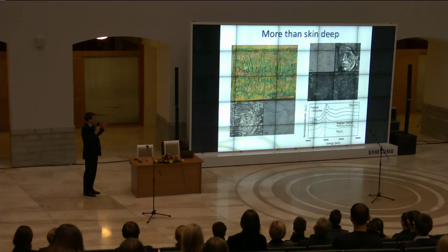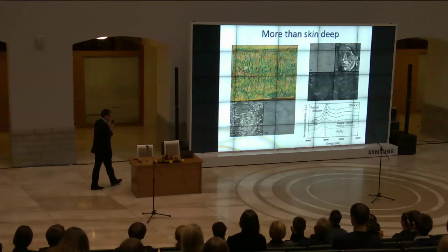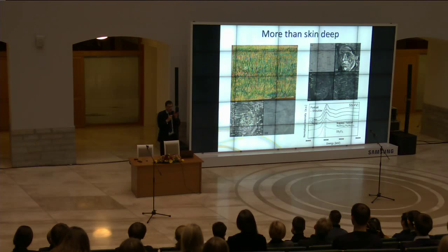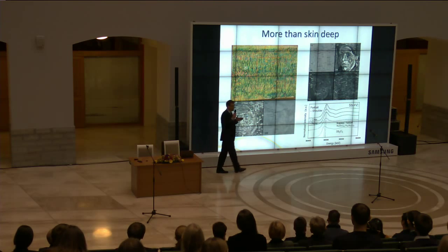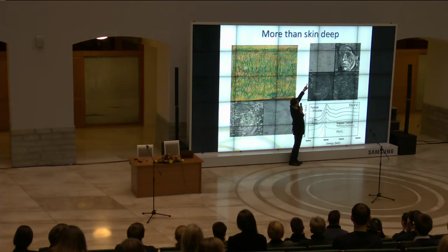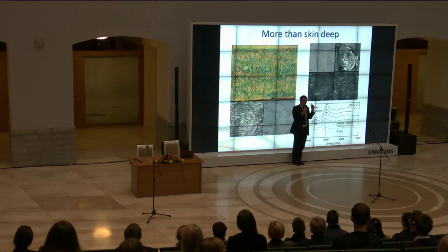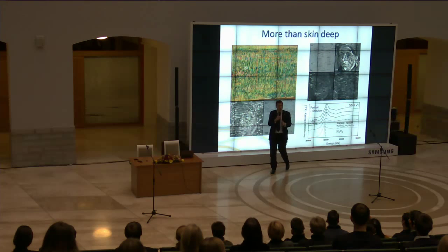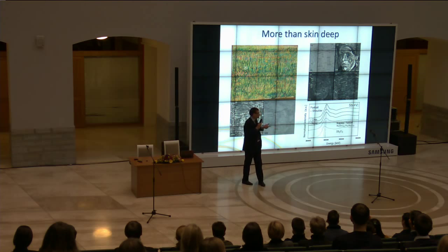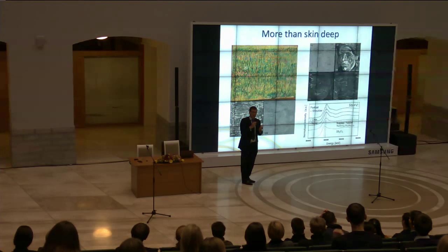The cleverer thing, however, is to determine exactly what elements there are in the image underneath the top coat of paint. And what people at ESRF did, and at the DESY synchrotron in Hamburg, was to selectively look at the emission of X-rays for different elements when the picture was irradiated with X-rays. So if you apply a filter and you say, where is the lead? You see this image here. The lead has no image of a face, it's uniformly spread. That's because the lead that's present in this was just a primer coat. It was an even coat of lead oxide. However, if you set the filter for antimony, which is the basis of yellow and white pigments, you start to see the image of a face, because some of the tones of the skin involved yellow or white.